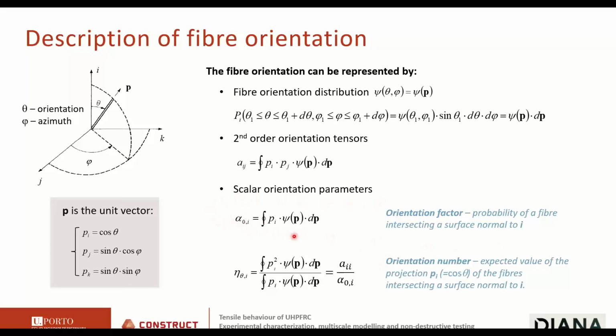So the fiber orientation factor. You have here the definition, but then I will go back to this. The fiber orientation factor can be seen as the probability of a fiber intersecting a surface normal to the direction I, okay? If this is a probability, it means that the maximum value of alpha is 1 and the minimum value is 0. So if alpha is 0, it means that you will not find fibers in your crack. If alpha is equal to 1, this means that all the fibers that you put will intersect the crack.